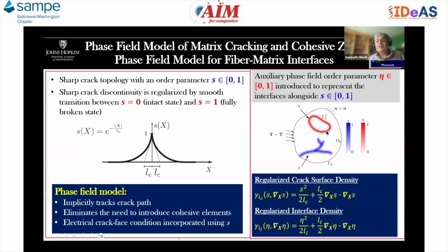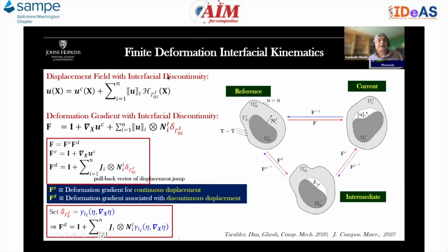And then the other advantage of the phase field is that I can introduce interfaces using the other order parameter. One is the order parameter S, which is used for modeling matrix cracking. This is a regularized matrix, a diffuse crack. And this is a diffuse interpretation of the interface that I'm using my variable eta in order to represent. So the eta variable is going to represent my interfaces corresponding to the fiber matrix interface. These are some of the kinematics that represent both the deformation as well as the gap opening due to interfacial decohesion here. I don't have time to go into this.